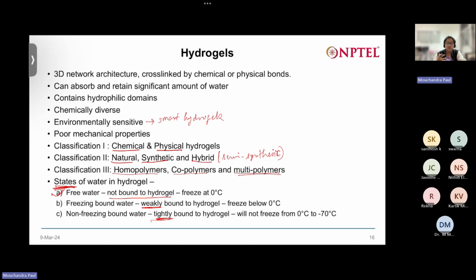So the free water will behave just like the water we drink. It will freeze at 0 degrees Celsius. Whereas freezing bound water, which is weakly bound, has the ability to freeze below 0 degrees Celsius, so maybe minus 14, minus 15, like that. Whereas the water molecules which are very tightly bound to the hydrogel will not freeze even up to minus 70. So if you want to freeze this water, you have to use liquid nitrogen, which is minus 196. Then you will get a hydrogel where all the types of water, whether weakly bound, tightly bound or freely available, will be frozen. And then you can use it for any application like freeze drying. Okay, so these are the three states of water that are found in hydrogels.